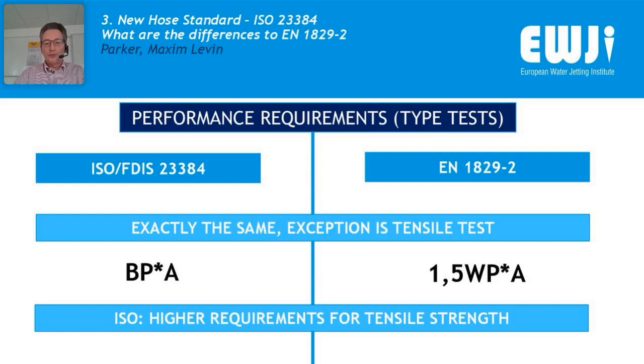And there is a small deviation on the performance requirements of the hose assemblies. In fact, they are exactly the same with a small deviation regarding the tensile test. Why is that? Again, in fact, if we are talking about mechanical requirements on hoses or hose assemblies, they shall withstand the loads which are induced not only by working pressure, not only by 1.5 times of working pressure, but also the forces induced by burst pressure. So in this part, ISO puts the higher requirements on hose assemblies compared to the EN standards. And all the rest is exactly the same.